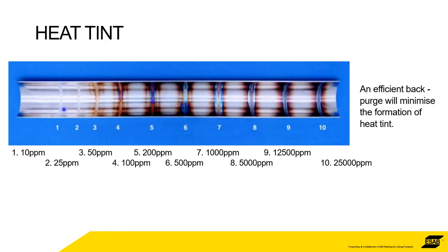So the chromium's not been able to react with oxygen and form oxides. Over at the other end of the scale, we've got 25,000 parts per million of oxygen, and you've got a very, very distinct heat tint there. So purging will minimize the formation of the heat tint.